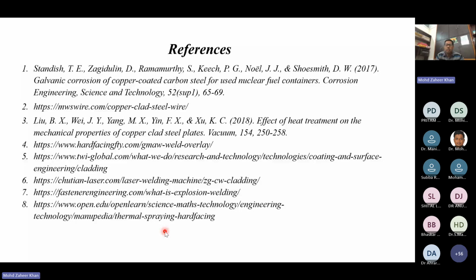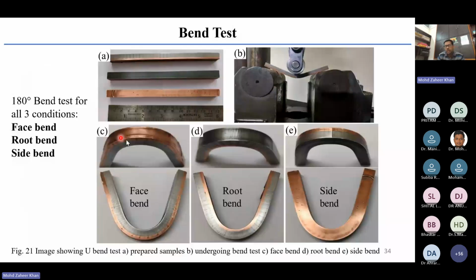So the main objective here was, what we want to see, we have got a layer of copper that has very high ductility. Its deformation behavior is completely different to that of the steel. So we wanted to see when more amount of copper is getting deformed, whether it is peeling off or not. So this test, that is the bend test that is carried out, was primarily to see whether in the case of extreme bending, when a lot of plastic deformation is given, the clad and the substrate layer are peeling off or any cracking has happened. So we found that nothing has happened. The peeling has not taken place. That is one thing that is quite successful. And the second most important thing is that if any brittle intermetallic may have formed, then cracking of the substrate or cracking at the interface would have taken place. So in both cases, this did not take place. I hope I am clear.